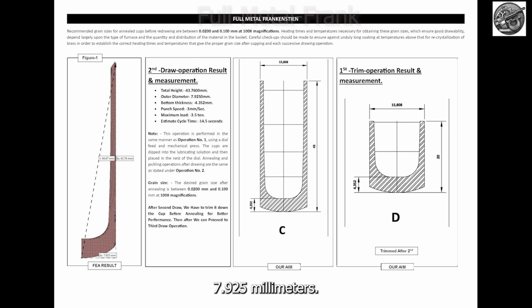Outer diameter 7.925 millimeters. Bottom thickness 4.352 millimeters. Total height 43.76 millimeters. Maximum load 3.5 tons. Estimated cycle time 14.5 seconds. After this draw, the cup undergoes annealing and pickling to restore ductility and refine the grain structure.